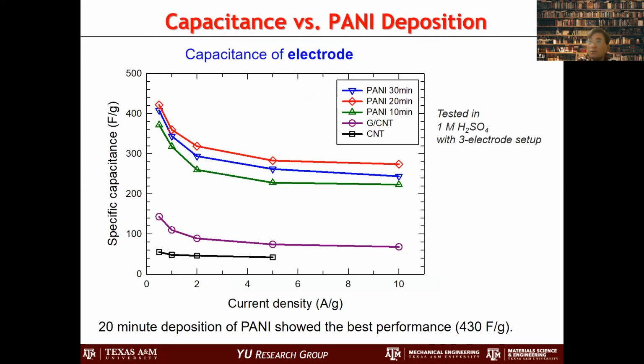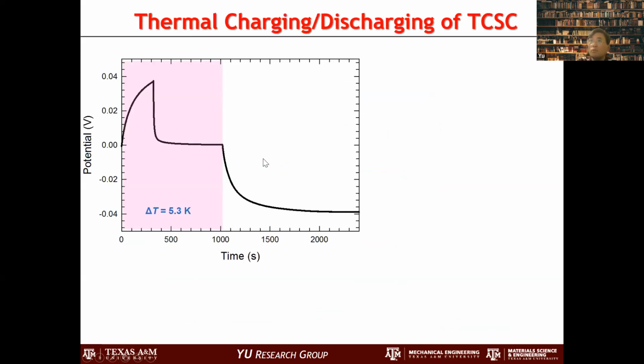So this is the capacitance, and because it's a capacitor, when we have only carbon nanotube, it's not porous, so the capacitance is not that high. But when we have graphene, it becomes a little bit higher. When we have polyaniline, which is a redox polymer, together, this becomes a pseudocapacitor, and then the capacitance becomes really high. So that's what we have developed. So this is a thermal charging and discharging behavior. When we have a temperature difference of 5 Kelvin, there's a potential here.